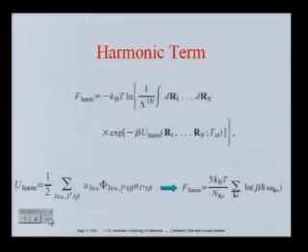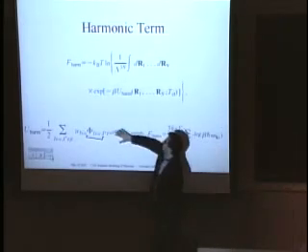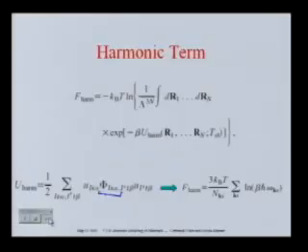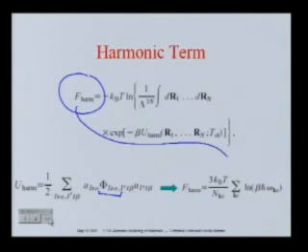So if you figure out with electronic structure codes the normal modes of your system, that is, the modes that give you an expression for the harmonic term that is diagonal in the displacement, and you find the frequencies, you can substitute this expression in here, work out the integral, and what you obtain is that your harmonic vibrational free energy is just given by a sum over the logarithm of all your vibrational frequencies. So this omega here would be your phonon frequency.